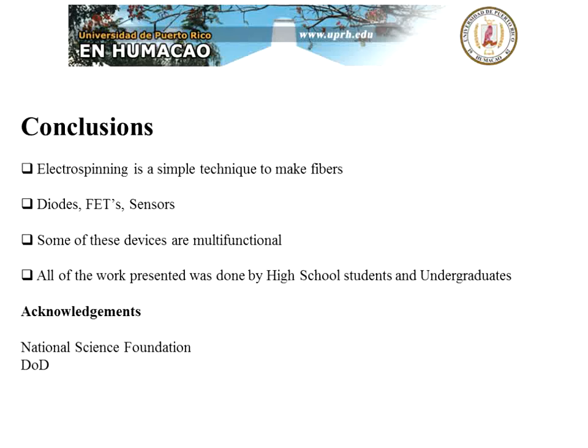in my presentation. And to conclude, all I would like to say is that electrospinning is really a very simple technique. The power supply that we have is about $750, but the rest is really cheap. And with this simple technique, you can make fibers of any polymer. If a polymer has a molecular weight typically around 300,000 or more, then you can make polymer fibers without having to add another plasticizer polymer that has a slightly higher molecular weight. So you can make fibers using the electrospinning technique.